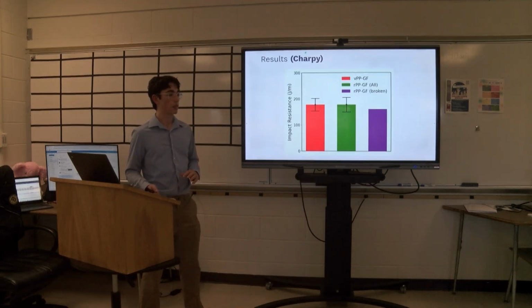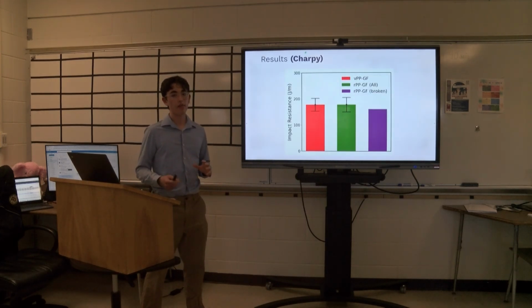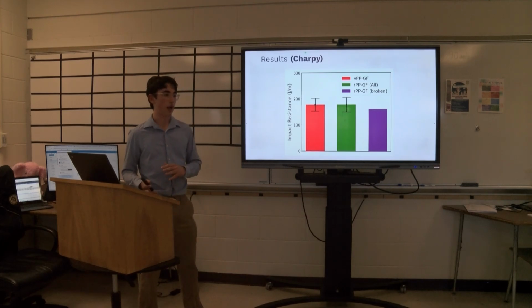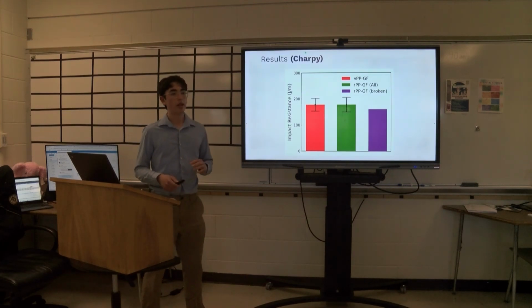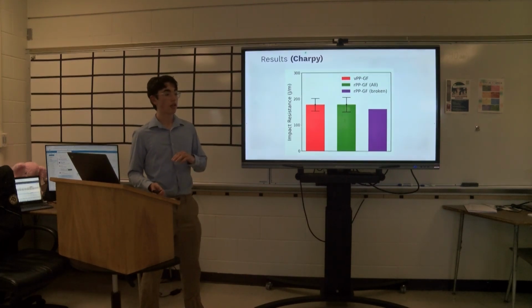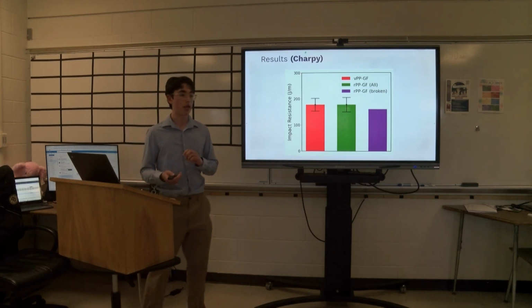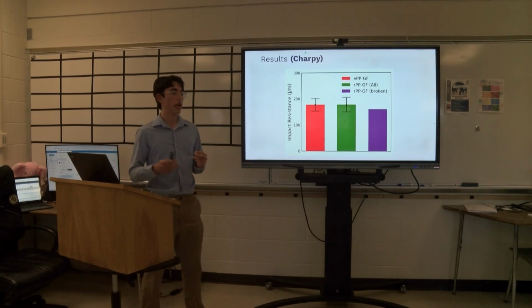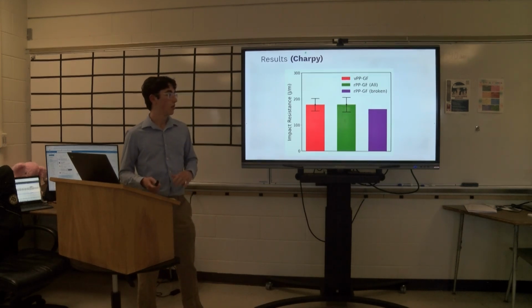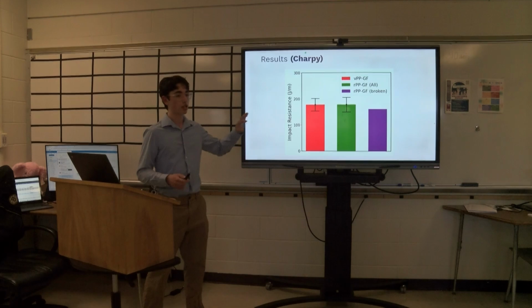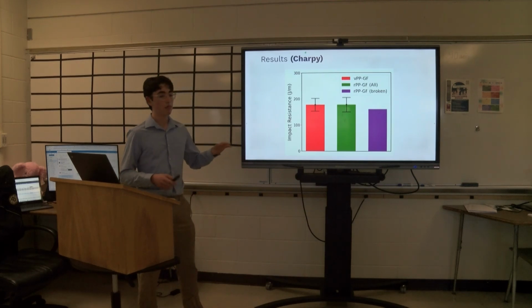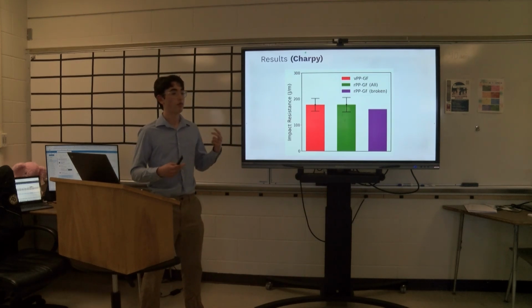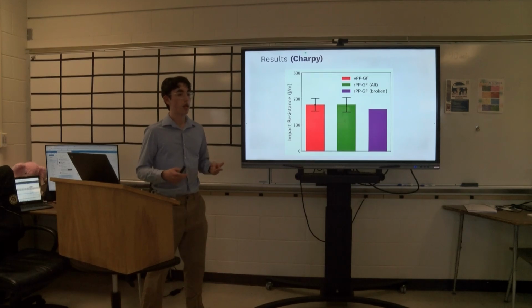Now, moving on to the Charpy test, unfortunately, 3 of the 5 Charpy specimens didn't fully fracture during the experiment. And this meant that the actual values for those are usually considered invalid. However, the fact that they didn't fully break also means that their impact strength must have been higher because it didn't break all the way through. So in light of this, the green column should actually be a little higher. The purple column I didn't compare at all because only 2 of the specimens actually broke, which isn't enough to make any significant conclusions.